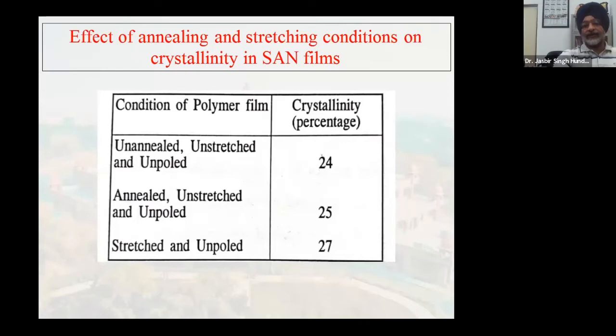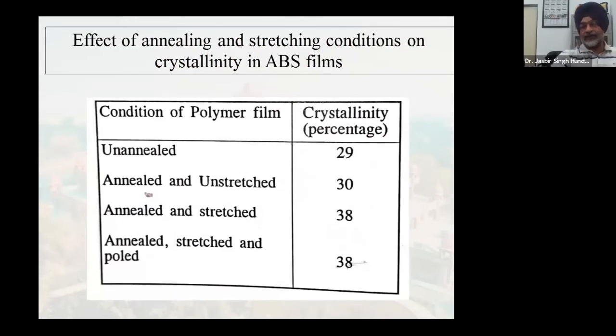So for unannealed, unstretched, unpoled films, in case of SAN, crystallinity was 24. Then by annealing, it increased by 2%. Stretched and unpoled, it went to 27%. And in case of ABS, we find that annealing and stretching increases the crystallinity in a big way. So for unannealed, unpoled films, it was 29, whereas it went up by another 9%, so it went to 38% in case of ABS.